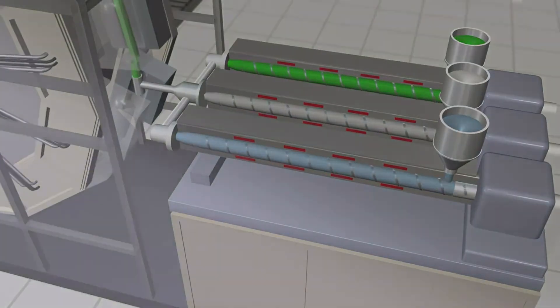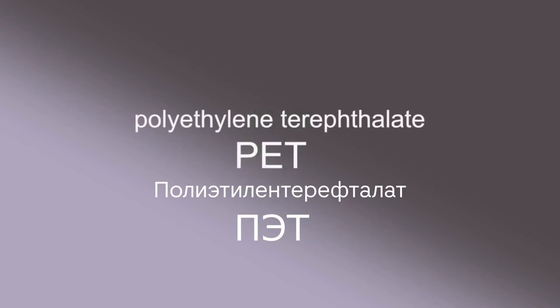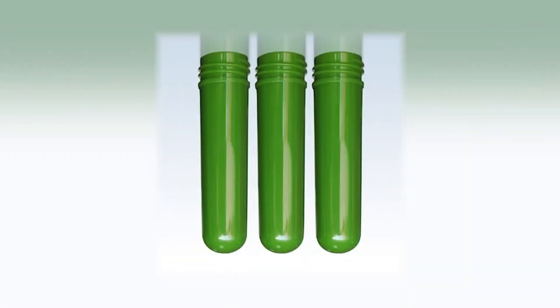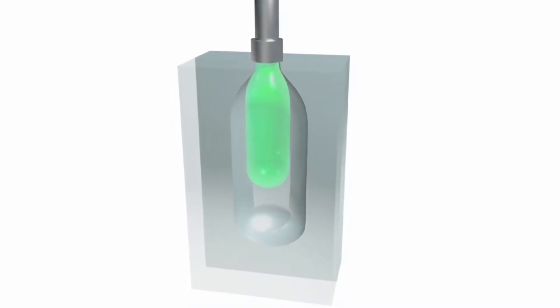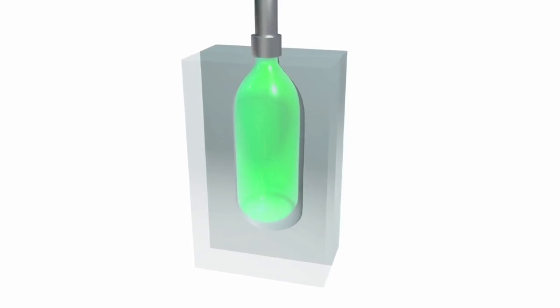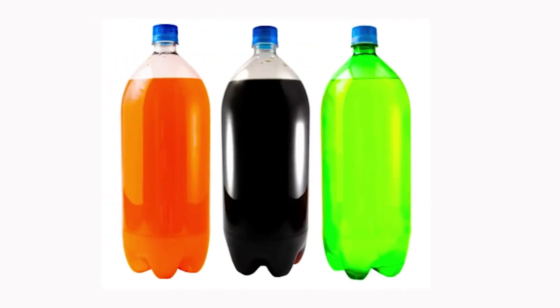The popular sales of plastic bottles for carbonated beverages has created a unique process for blow molded bottles made specifically from polyethylene terephthalate, or PET. For PET blow molding, bottles are first created in a test tube shape — injection molded preforms — and then, in a separate operation, reheated and blown into their final shape. This two-stage process creates bottles that we, as consumers, know to be thin-walled, yet capable of containing gaseous carbonated beverages without losing pressure or exploding, even if they are dropped.